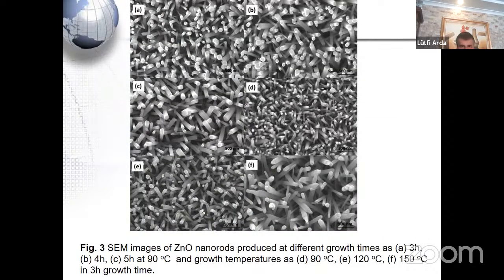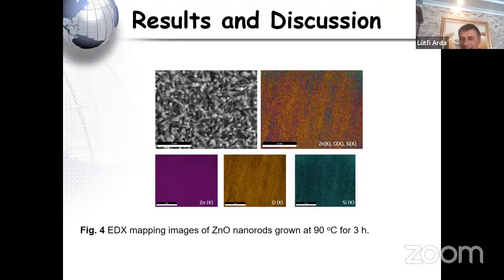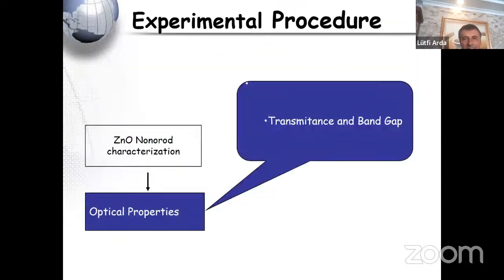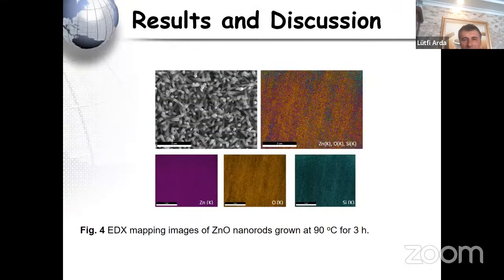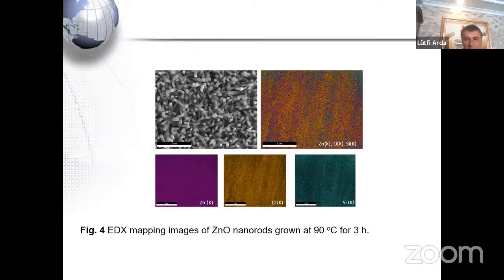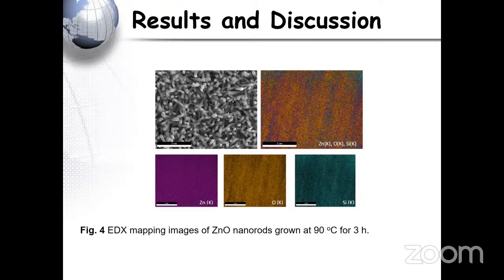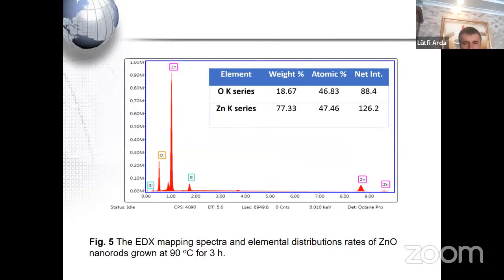Okay, let's go fast. This is the EDX. I'm sorry for this. These are the EDX mapping images of zinc oxide nanorods, the elemental distribution of the elements. The first one is the mapping, and the second one is the EDS mapping spectra and distribution of zinc oxide nanorods grown at 90 degrees Celsius for 3 hours.